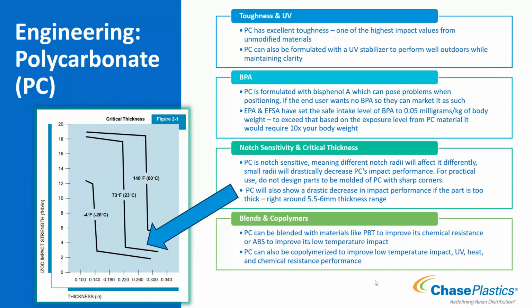That means nothing if you don't know the exposure of the material you're seeing. With polycarbonate, the exposure level you would have to bisphenol A based on products made of polycarbonate - you would have to come in contact with, or eat or drink food or beverages that come in contact with polycarbonate, at an excess of 10 times your body weight to even get to that exposure level. So BPA is a concern, as with anything, it can be, in very high levels. Polycarbonate has BPA, but the exposure to it is very, very low, so it would be very difficult, hopefully impossible - we're not eating or drinking 10 times our body weight - to reach that threshold for exposure to the BPA in polycarbonate. Just wanted to point that out. Obviously it's a thing, I'm sure questions will surround that, but it has to be talked about, right?